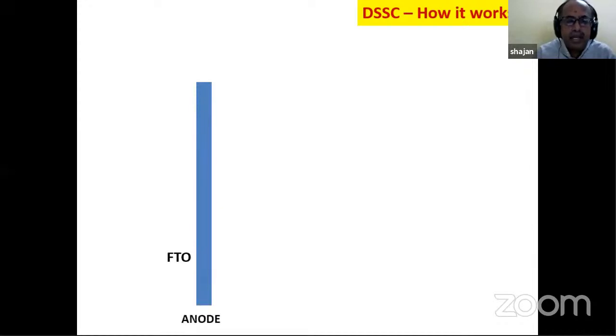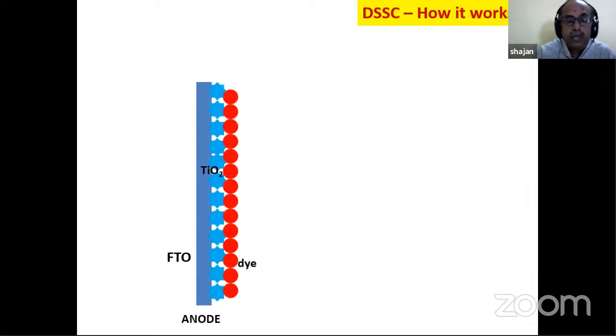Now let us see how the dye-sensitized solar cell works. It has one substrate, a glass substrate, or what you call fluorinated tin oxide. It is a conducting tin oxide, normally called TCO, through which light can be transmitted. It's just like a glass slide on which fluorinated tin is coated, and we call that an anode. Above this, we coat the titanium dioxide, and above that, we coat the dye. The titanium oxide and the FTO together we call a photoanode, because it is related to the light. That is why it is called a photoanode. And above that, a dye is coated.